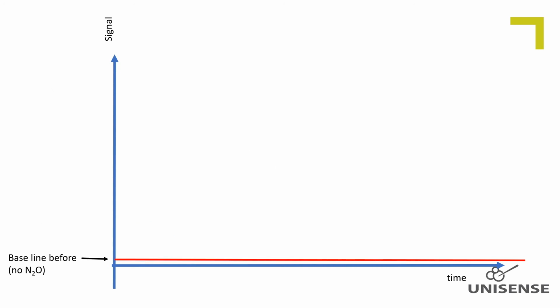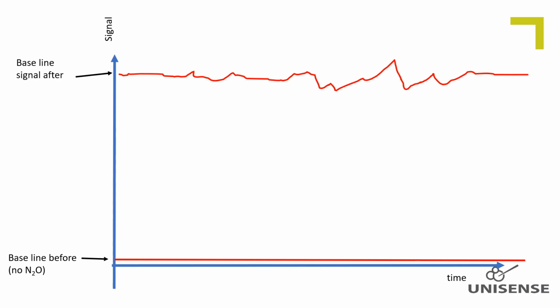A physical impact, like a drop, could also damage the glass insulation of the platinum wire connection to the working electrode. This will typically result in an elevated and noisy baseline signal due to exposure of polarized platinum to the electrolyte. Chemical reaction taking place on the exposed platinum surface will create a current which will overlay the working electrode generated current. The size of the baseline increase will depend on the degree of damage to the platinum wire insulation. Such damage can not be repaired either.